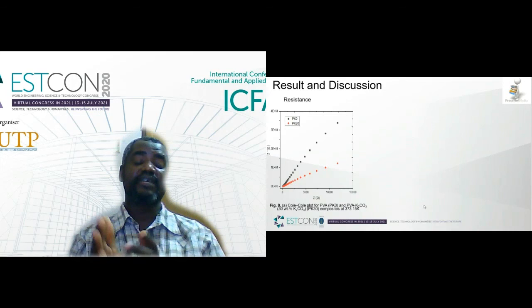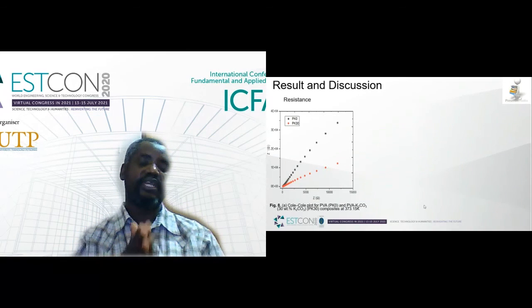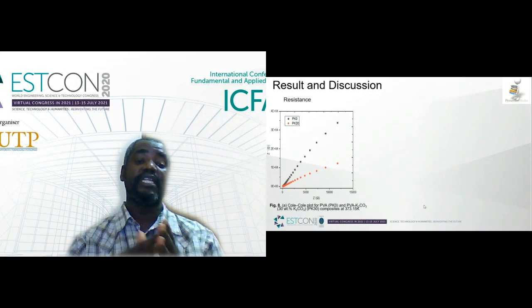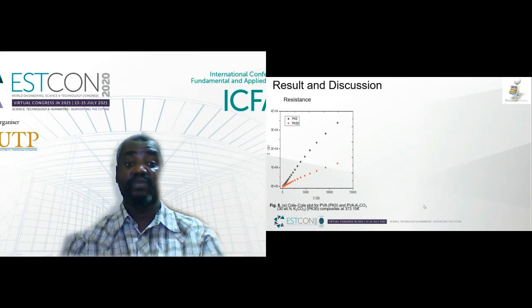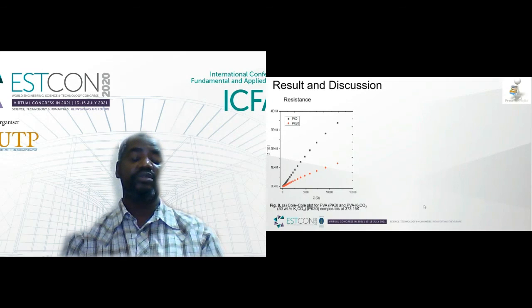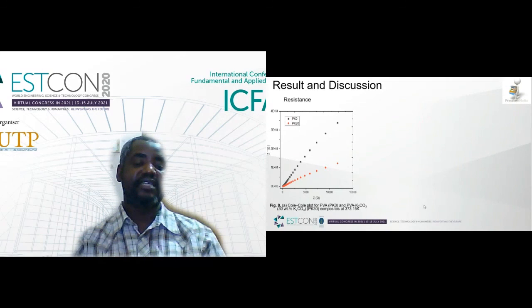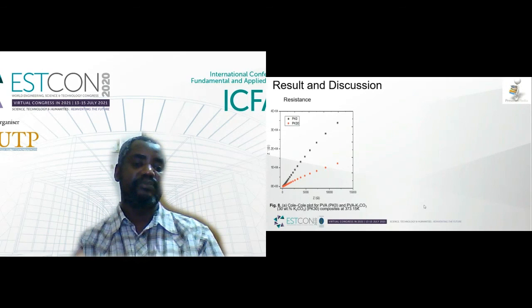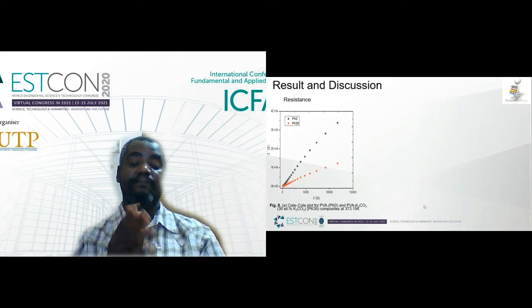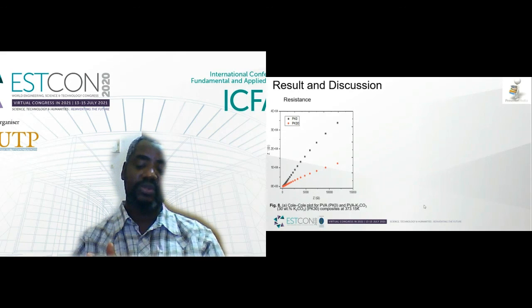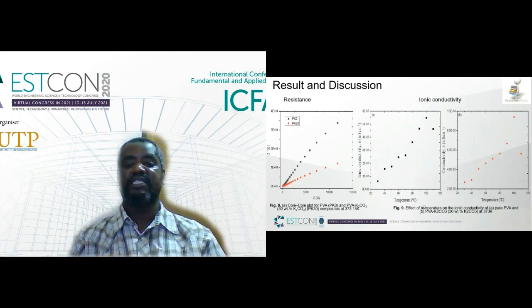As can be seen here, after EIS analysis, electrochemical impedance spectroscopy, both electrolytes show a spike in both the lower and higher frequency regions, showing a double layer formation. From the EIS plot, we were able to extract the bulk resistance from the axis of the impedance analysis. Based on the bulk resistance, we were able to compute the ionic conductivity for the electrolyte at different temperatures.